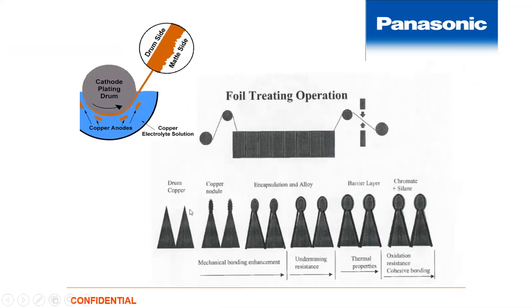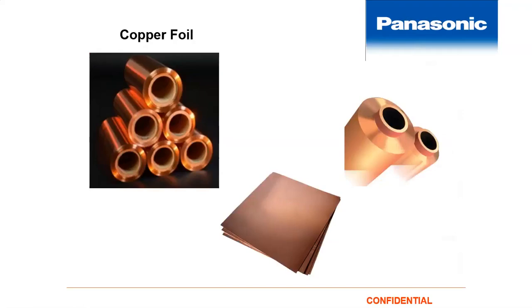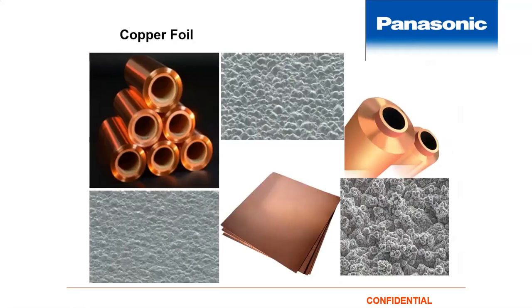Once that's created, there still are several processes that it goes through, and that's a treating process that the copper manufacturers run them through, typically to grow some nodules to help improve bonding, encapsulate the alloy, and make a barrier layer for thermal resistance and undermining resistance. And then at the end, an oxidation treatment so it doesn't oxidize, and a chromate silane finish that goes on there to prevent it from corroding. So those are all the steps that go into making copper foil as we know it, and those are pulled off into rolls.